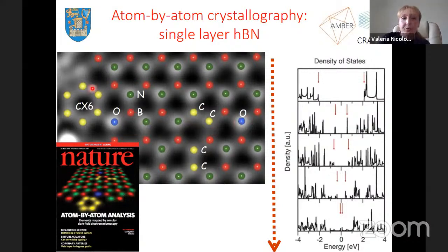So we learned from this that we could indeed start tuning inclusions of carbon, and by doing that, we could shrink the band gap, really, and we could go from an insulating material to a heavily doped carbon boron nitride, shrinking the band gap. And this was something very, very useful to know when some colleagues went ahead and did some devices with it.